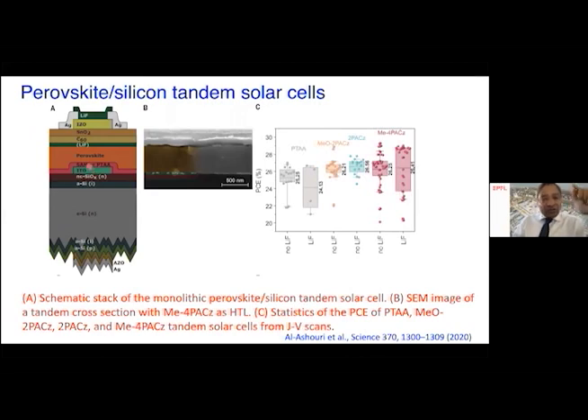On top of the recombination zone, the hole transporting material, it's a SAM, that's a self-assembled monolayer, or PTAA, this is a polymer. We will see the structures later. These types of hole transporting materials are deposited, followed by the perovskite solution processed on top of this wafer, and the lithium fluoride, then the carbon C60 as electron injection layer, followed by the electron transporting layer, followed by tin oxide, and then we have a conducting substrate on top of the tin oxide layer.